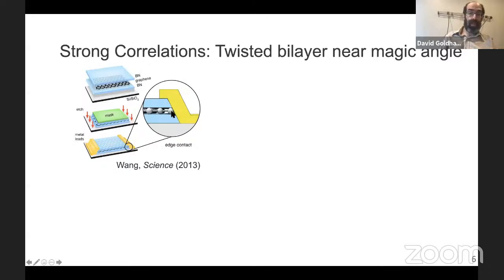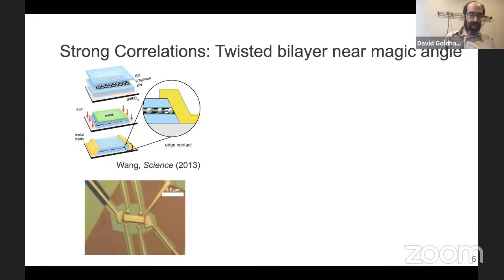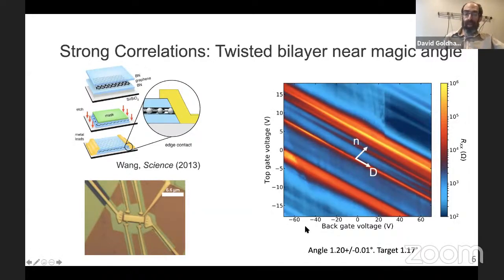This is coming from work from Columbia, showing that you can make extremely robust contacts to just 1 nanometer or so that's poking out of the graphene at the side, so you can leave most of it protected. And so here's an example of a completed micrograph of a sample that we've made, and you can see that there's metal on top. That's a gate electrode. There's also a gate below, and so by tuning these 2 gate voltages, you can see that there are features in conductance that we measure through this structure. In this case, we're plotting a resistance, and you can see there are features that have some systematic behavior in these 2 gate voltages.